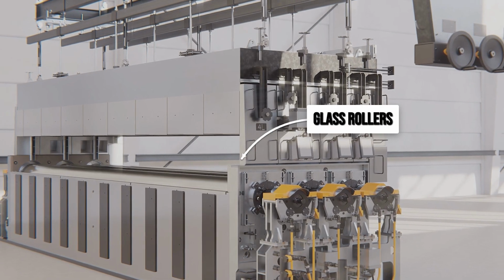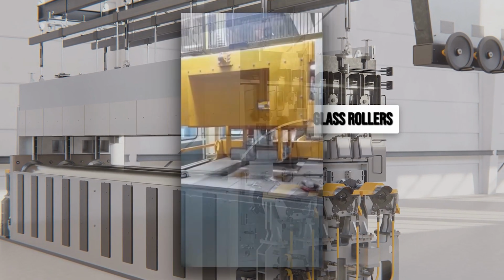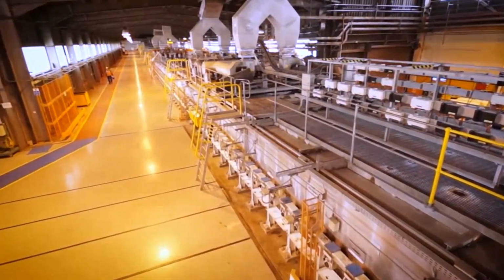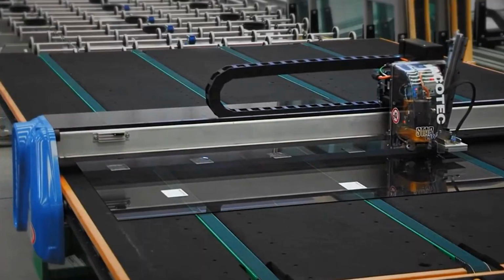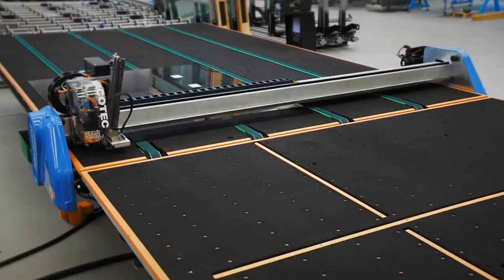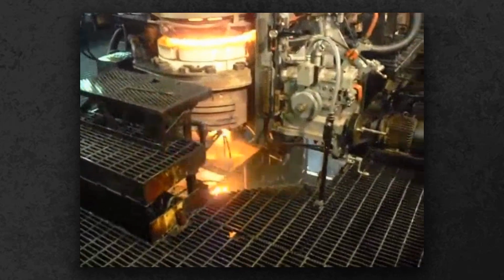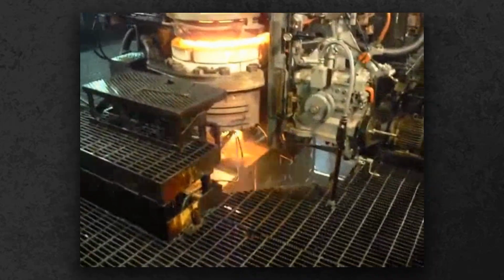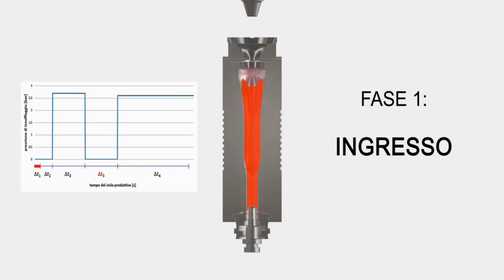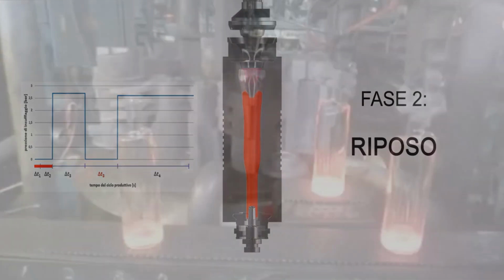Every meter, the chemistry above the tin keeps oxidation at bay, while operators monitor sensors and occasionally skim away tin oxide dross with specialized paddles. As the ribbon cools, it travels forward, gradually solidifying before robotic blades slice it into panels as long as a city bus. Meanwhile, container glass follows a different choreography. Molten gobs, each precisely cut, drop into cast iron molds. High-speed machines inject bursts of compressed air, shaping the glass into bottles or jars in a matter of seconds.